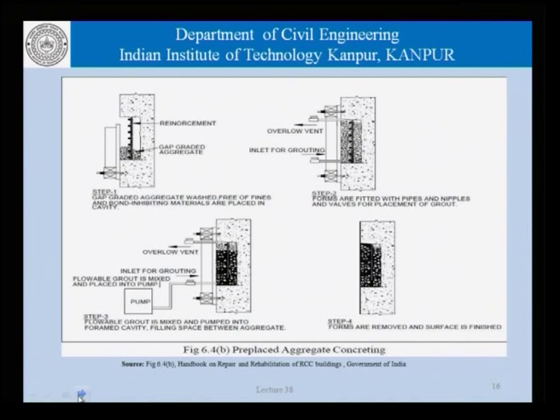These are some more pictures from pre-placed aggregate concreting operations. The first step is to fix the formwork and place gap graded aggregate, washed, free of fines and bond inhibiting materials, in the cavity. We could use reinforcement here if we want, followed by forms fitted with pipes and nipples and valves for placement of the grout. So, all these paraphernalia is added to this system.